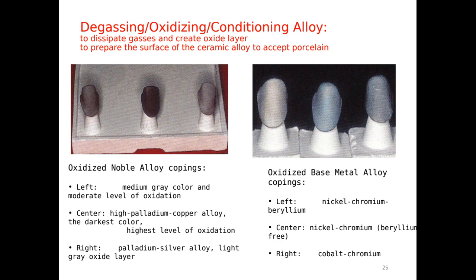So let's take a look at the picture here. We have the oxidized noble alloy copings versus the oxidized base metal alloy copings, and we see the different colors. The noble alloys are on the left, the base alloys on the right. In the left picture, the first one is a medium gray color with a moderate level of oxidation. In the center, the high palladium copper alloy has a darker color, the highest level of oxidation, and the right, palladium silver alloy, has a light gray oxide layer.